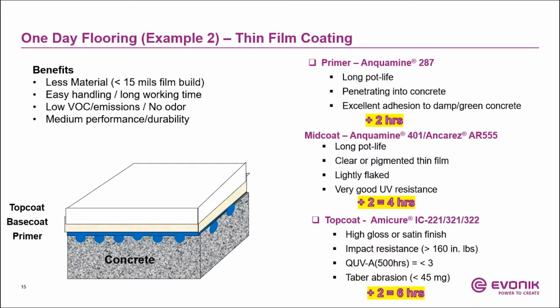The key thing is that you want to make sure that the moisture comes out from the coating. So you want to make sure that 287 is completely dry, moisture is out, and generally after 2 hours of application, moisture comes out. All you want to make sure is, again, you have good ventilation so the moisture can leave the substrate before you apply the polycarbamide technology.